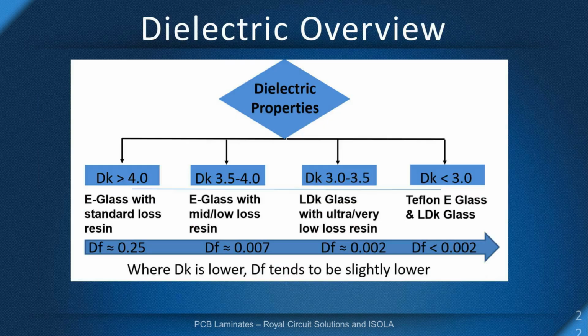All right. These are kind of, as John had touched upon before, some of our divisions and how you would describe what kind of dielectric, what kind of resin you want to look for. We've already discussed the E-glass versus the low decay glass, and you can see here how that does affect your decay. If you're using a standard resin and an E-glass, you're going to be around 4.0 and a little bit higher. When we go to the lower resins with that still standard E-glass, you still are around 3.5. And then when you go to the Teflon and low decay glass, that's when you really start to get below that 3.0, and your dissipation factor is much lower at a .002.